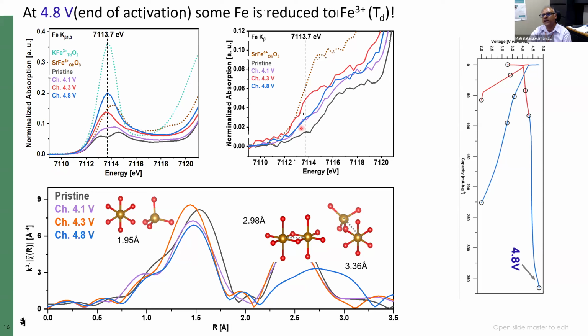So one does not expect a reduction of iron, but this reduction of iron can also be seen in the K beta 1,3, where there is an increase in this pre-edge peak, which we believe is because there is some iron which is moving to tetrahedral sites, and iron 3+ in tetrahedral sites would show an increased pre-edge intensity.